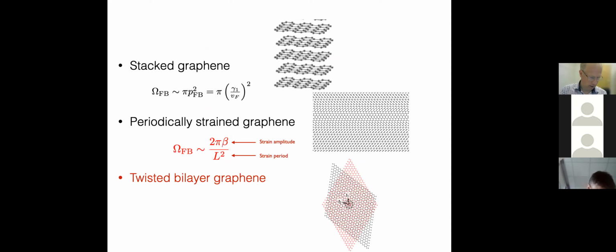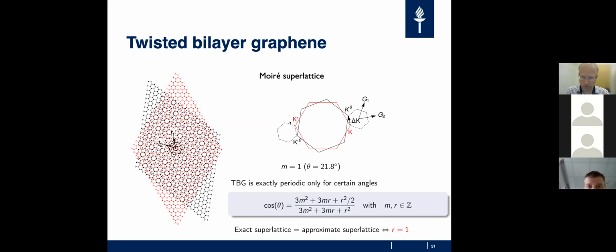Okay, my last topic, I guess I still have a little bit of time to mention it, is twisted bilayer graphene. Another way to get flat bands from graphene is to twist it. So now, instead of going to this full Bernal stacking twist, we consider an arbitrary twist. In this case, if you put two graphenes on top of each other, what you can see is a moire superlattice. One way to understand this moire superlattice is to take the reciprocal lattice of graphene, take two of them and twist those with respect to each other, and then there is a nesting vector that defines another Brillouin zone for the superlattice.